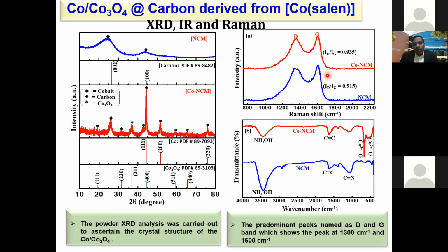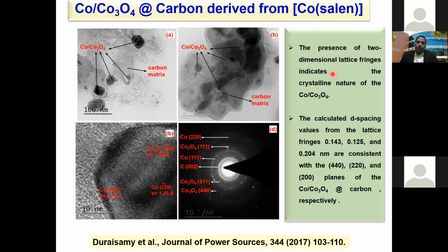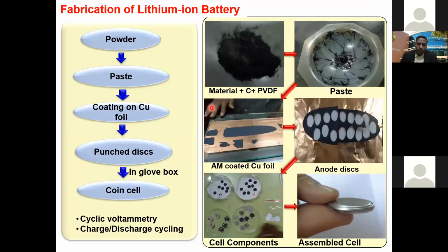You can note that the ID by IG ratio, the intensity ratio of the D band to the G band, is close to 1. It is mostly graphenic carbon that is present. The formation of cobalt oxide on the carbon matrix has also been characterized using electron microscopy observation. What you can see is we have a metal oxide on the carbon matrix. So this carbon matrix is expected to provide a conductive pathway by decreasing the resistance, and also a buffer for change of volume.